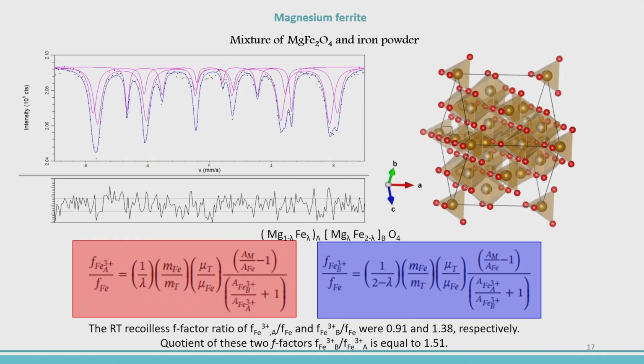And finally, we did that in the third ferrite. This is again the same. We have to start with what we guess about the distribution of iron in the two sites, and then we derive these two, and then we again do all experiments as before, and we get a value that is not equal either to nickel ferrite or to magnetite. It is different. So what we have found is that we have to be careful: we cannot use the same F factors for all ferrites. Don't use that of magnetite, because it can be different.